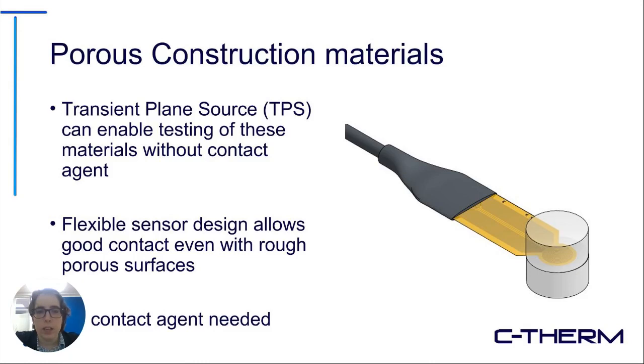The other advantage of using the flex sensor for these kinds of construction materials is that, especially with concretes and brick and those types of materials, they can be quite abrasive, and that can have the risk of damaging some of the more delicate types of methods out there. So, because the flex sensor is, as the name would imply, quite physically flexible, it's much less likely to risk being damaged when you're testing with a rough surface or a highly abrasive material.